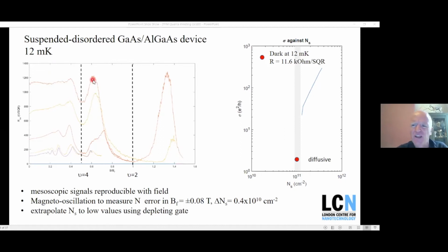We had to rely on the fact that they're insulating in the dark and just use an in-situ LED device to illuminate. We already see some very low field magnetoresistance, weak localization. We see this noise effect. You might say, well, Stuart's no good at doing measurements. They're full of noise, but it's actually reproducible noise. It's actually conductance fluctuations. I've plotted this as a function of filling factor, and as you change the carrier density, they all line up.